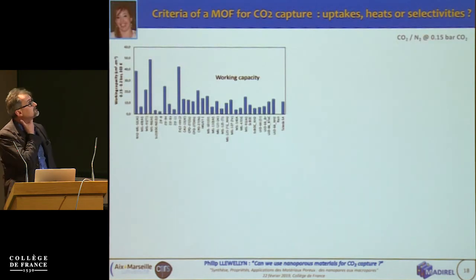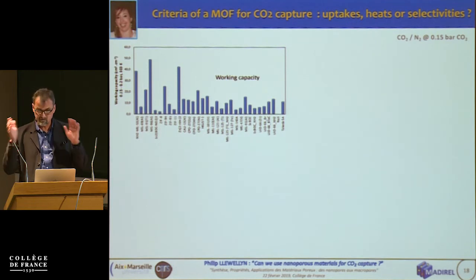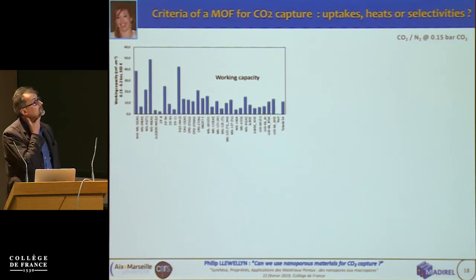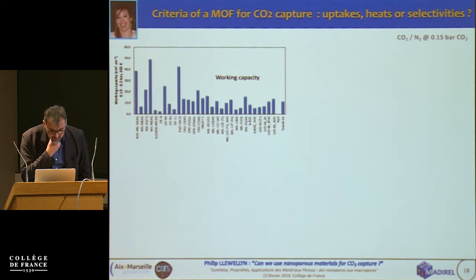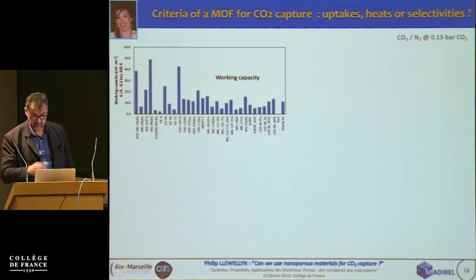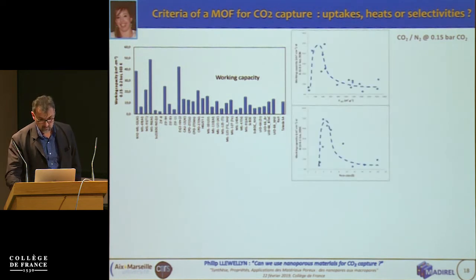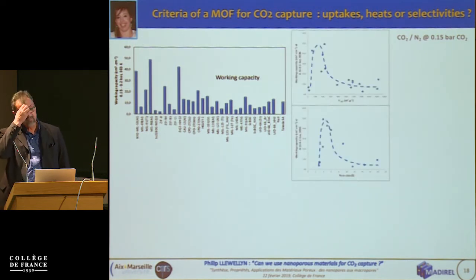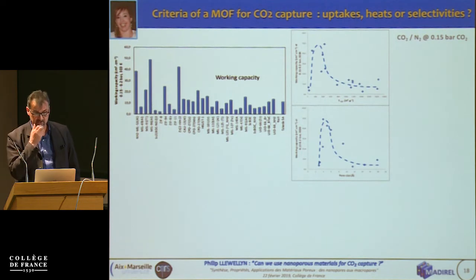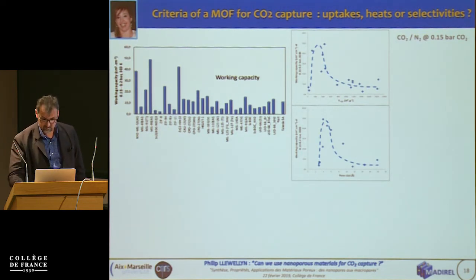So this is what we did with Virginie, for example. Look at things like working capacity, so the amount adsorbed over a different pressure range. And this is for CO2 and nitrogen at the post-combustion conditions. So these are a whole series of different MOFs. On the right-hand side, we're comparing with the Takeda 5A, which is a carbon. And we can see that we can sort of relate the best uptakes with a variation in pore size, for example, or a surface area, but I think they're both more or less related.